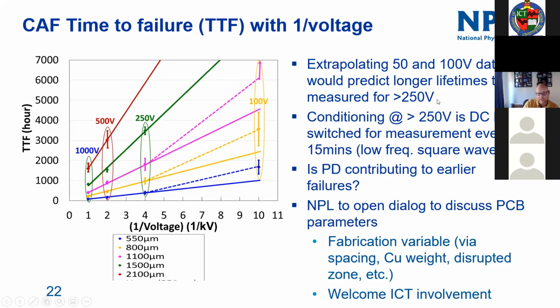Now, the conditioning of these boards is DC at 1,000 volts and 500 volts, but we are switching the conditioning voltage out every 15 minutes or so to do the measurement, and then switching it back again. So that's equivalent to a very low frequency square wave.